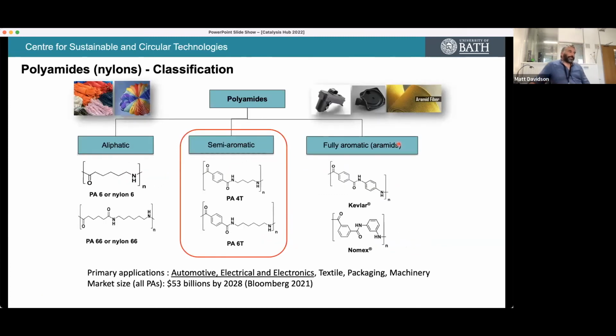So polyamides are interesting materials. There are aliphatic ones, semi-aromatic ones, and fully aromatic ones, so we go from nylon all the way through to Kevlar. These semi-aromatic ones are high-performance polymers, with typical applications in automotive, electronics and electrical, sort of structural engineering polymers, if you like. So they're really important commercial polymers. Typically, terephthalic acid is used, and the numbering system is polyamide 4T, polyamide 6T. So the aliphatic chain is 4 or 6, and that numbering system follows all the way through.